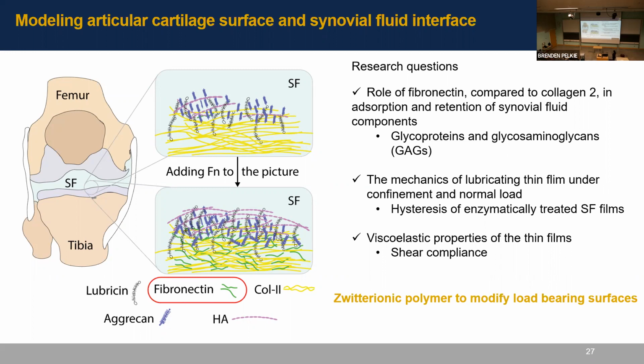So in this project we want to see what the role of fibronectin is, in comparison with collagen type 2, in forming the synovial fluid thin film, as well as retaining it. Synovial fluid is a very complex fluid, and so we looked at only the role of glycoproteins and glycosaminoglycans. Using SFA, we measured the nanomechanics of the thin film under normal load and confinement, and see what the hysteresis of the different types of synovial fluid film is. We can also get viscoelastic properties of the thin film that is formed and measure the shear compliance or the shear modulus of the thin film.